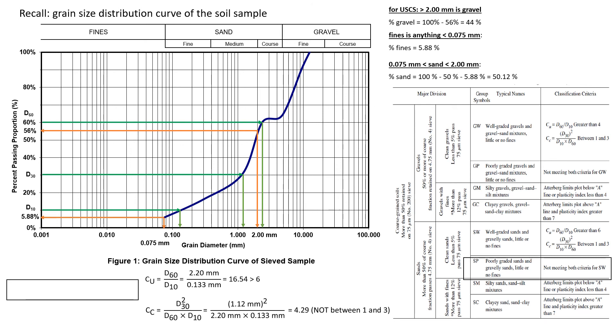For 60% passing proportion, the diameter size is 2.20 millimeters. For 10% passing proportion, it is 0.133 millimeters. The coefficient of uniformity Cu = D60/D10 = 2.20/0.133 = 16.54, which is greater than 6, so the uniformity criterion is met. For the curvature coefficient Cc, the diameter for 30% passing proportion is 1.12 millimeters. Cc = (D30)² / (D60 × D10) = (1.12)² / (2.20 × 0.133) = 4.29, which is not between 1 and 3, meaning it does not meet the well-graded criteria.